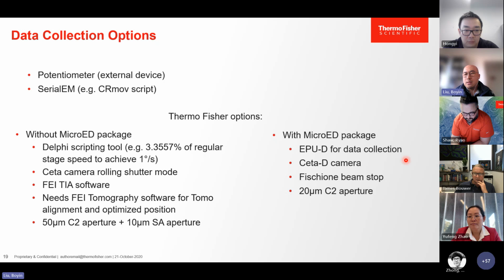With the MicroED package, the situation will be much easier. You can use EPU-D automation software for data collection. You have a Ceta-D camera for which movie mode is available, and you have a smaller beam stop, a Fischione beam stop. And you also can use a 20 micron C2 aperture. In that case, the 20 micron C2 is the limiting aperture. You don't really need a selected area aperture anymore. The 20 micron C2 already gives you a very good signal.